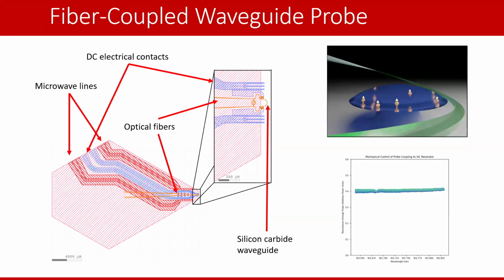So what did we do? We put together a silicon carbide based waveguide probe, a completely separate chip to bring close to the whispering gallery mode resonators. And by bringing this separate chip close by and then actually touching the silicon carbide waveguide on this chip to the resonator like so, we can control the optical coupling to the resonator system.